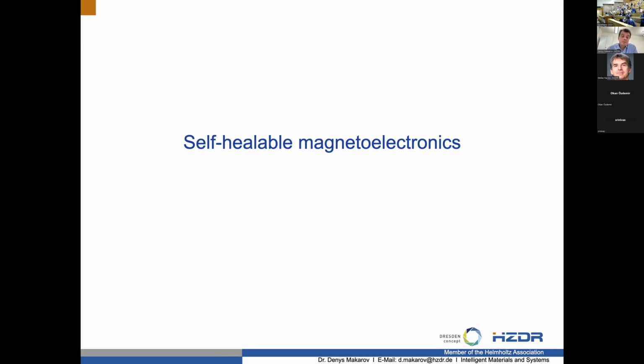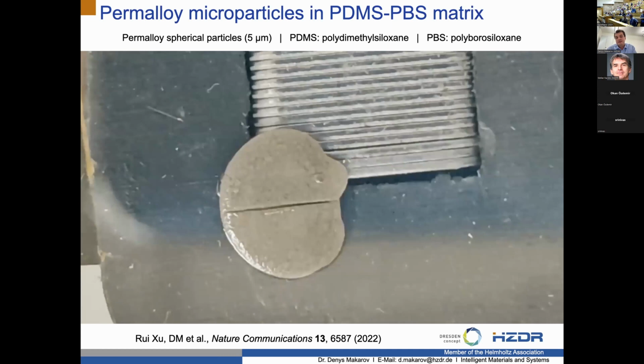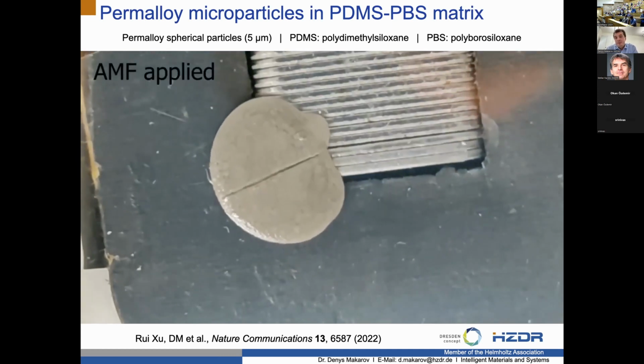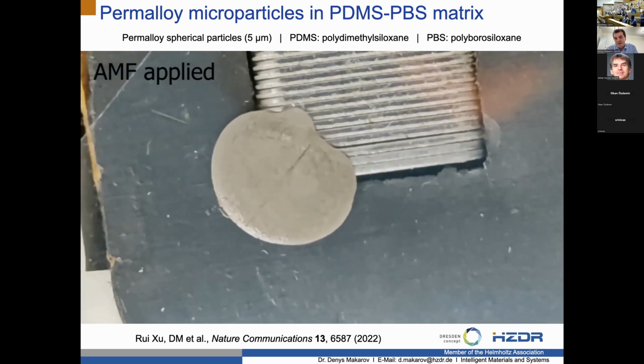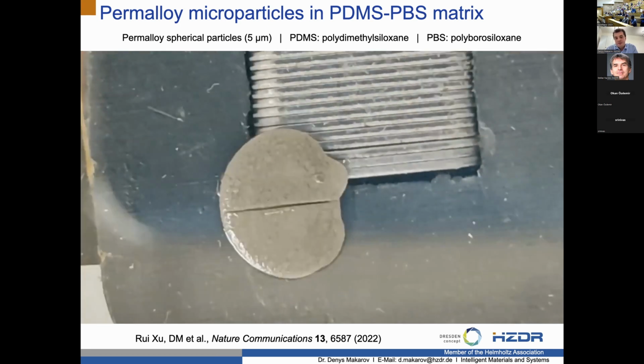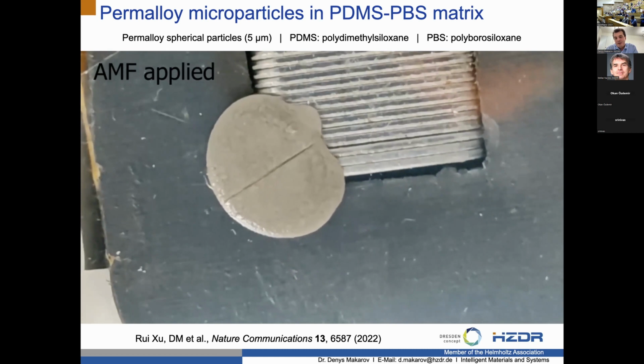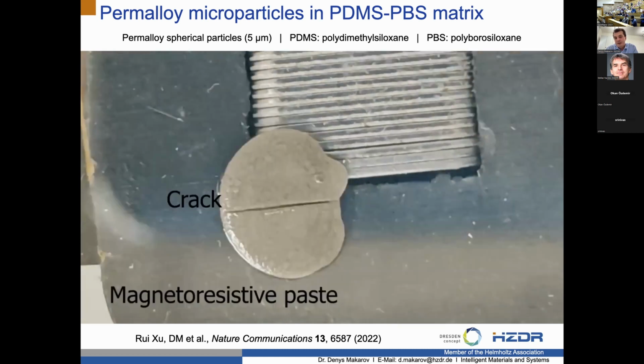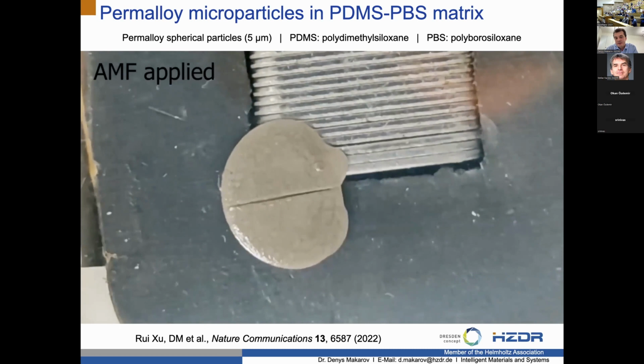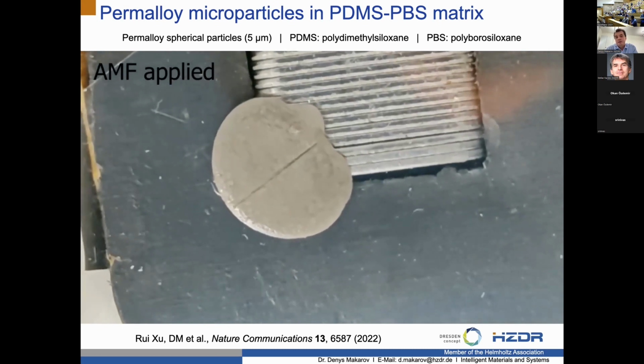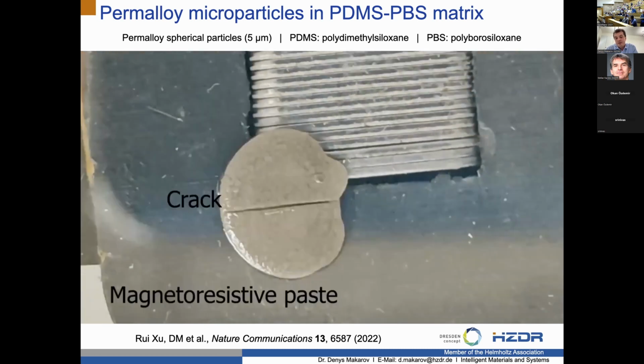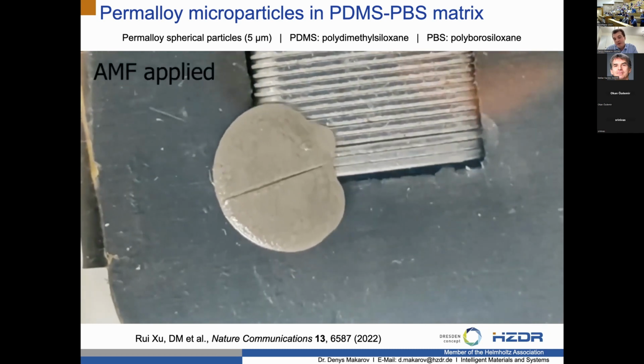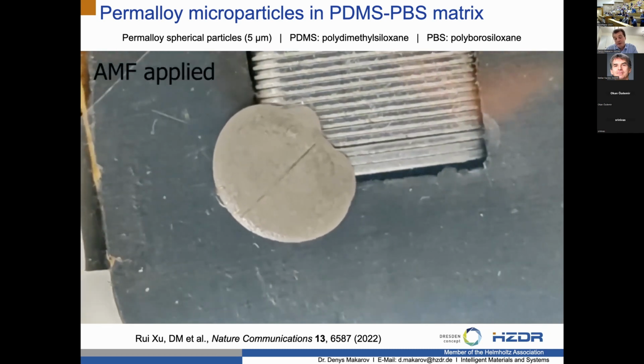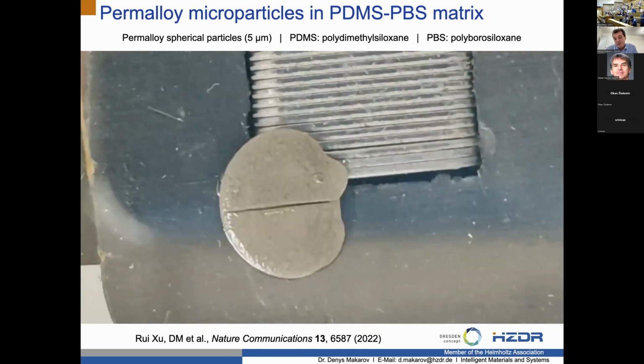Now you can do a very interesting trick. You can use polymers which have so-called dynamic bonds. If you have highly dynamic bonds, you can realize such kind of composite. PBS, polyborosiloxane, is a standard material which has exactly the properties of dynamic bonds. You can reinforce it with PDMS, a synthetic rubber, polydimethylsiloxane, and put in the magnetic content like permalloy particles. And what you see here is a composite which looks like a slurry a little bit, and it has a crack. You can simply cut the crack through this composite.